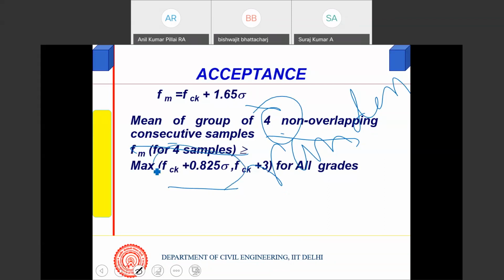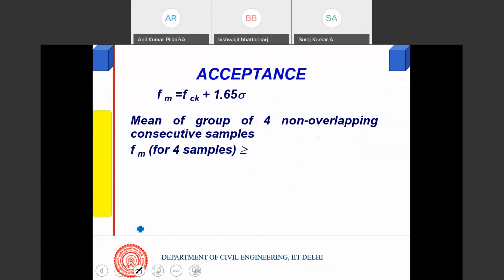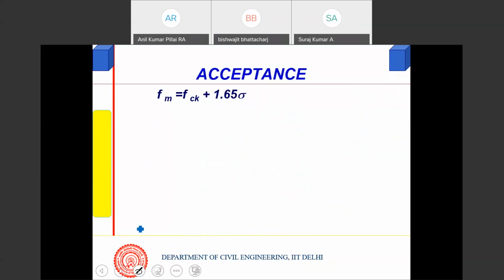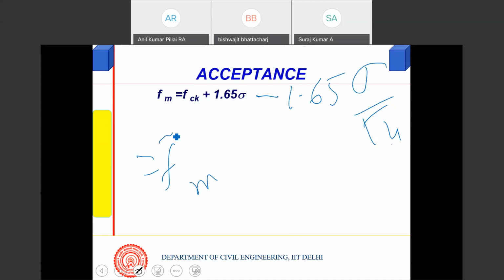Now, what is this? FCK plus 1.65 sigma is the target mean. Let me just clean it up. This is the target mean. Now, if you have taken 4 samples, this can have a variation, and the minimum it will have is 1.65 sigma under root 4, because you have 4 samples and you are finding their mean. So this is sigma by 2. They have deliberately taken 4.